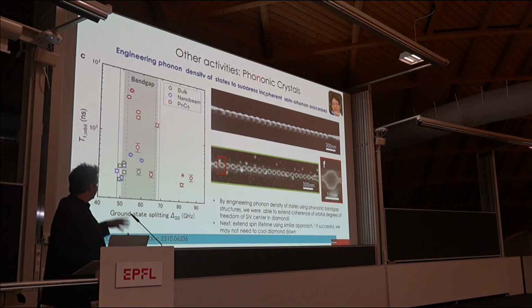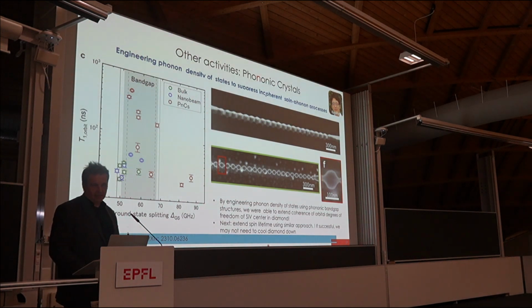And with that, without going into detail, we were able to show that we can extend coherence of orbital degrees of freedom. We can suppress phonon-driven processes, but we are still working to show that this has a positive impact on spin. It's a challenging measurement. We think the answer is yes, but it's a challenging measurement.